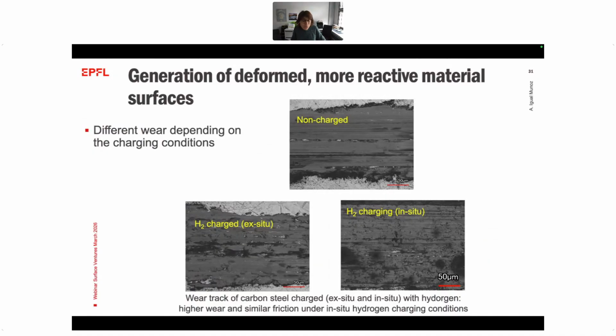In this case, we have thicker and higher cracked surface in the charging condition. This is ongoing work, of course. We are now trying to understand this interaction, hydrogen and material, but still developing the smarter way of carrying out this test to answer the question of the interaction hydrogen-metal under tribological conditions.